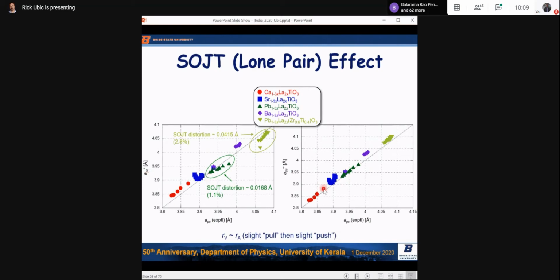Again, A prime, A double prime. The only negative errors are here for the lead compositions. If we add a little bit, in this case 0.0415 angstroms, 2.8%, we can eliminate those errors. So again, I think that's a way of quantifying the strength of the lone pair effect.